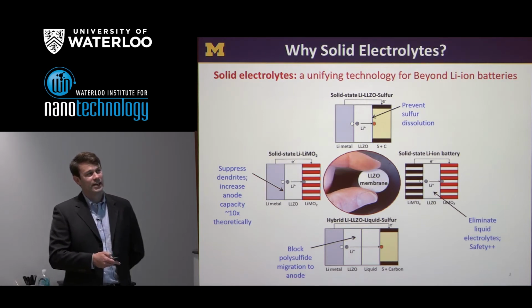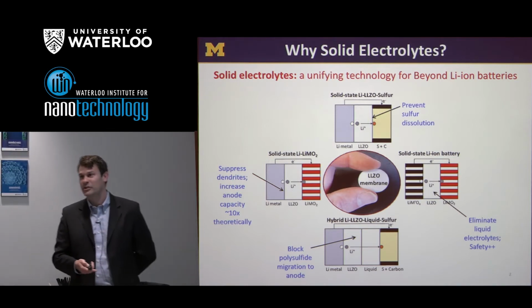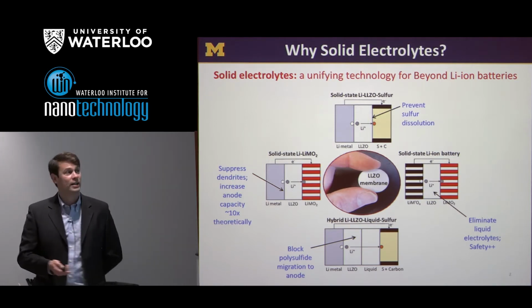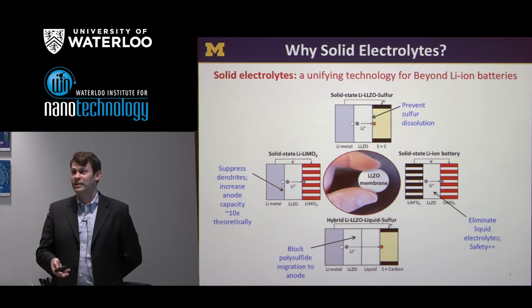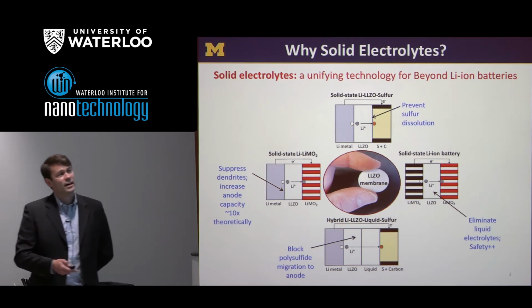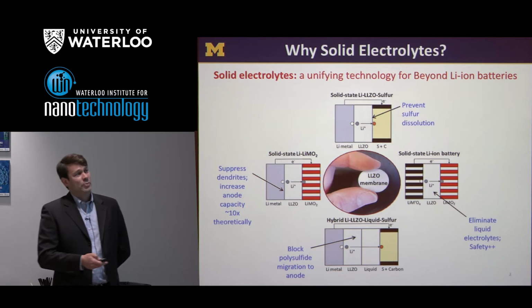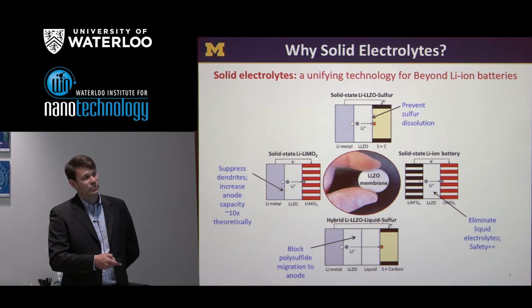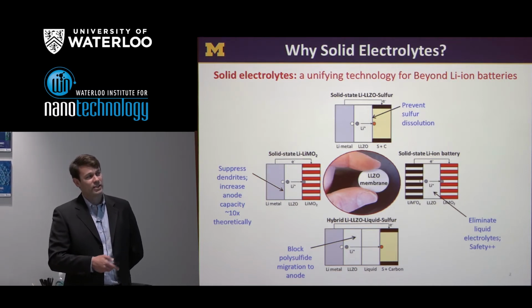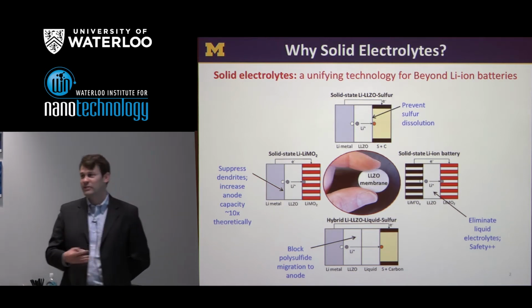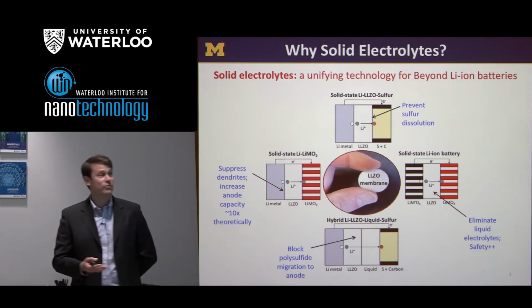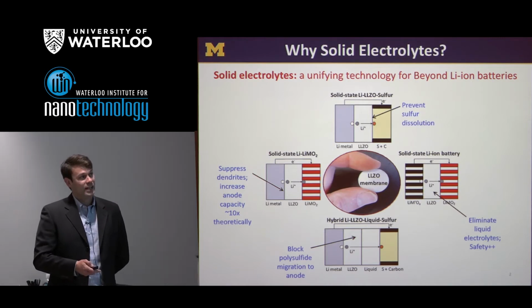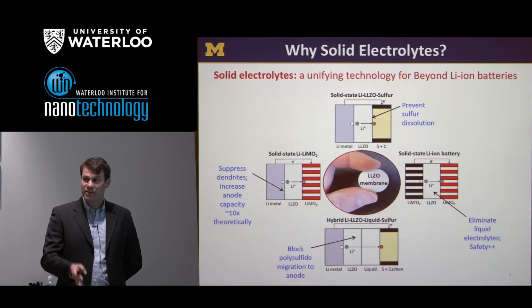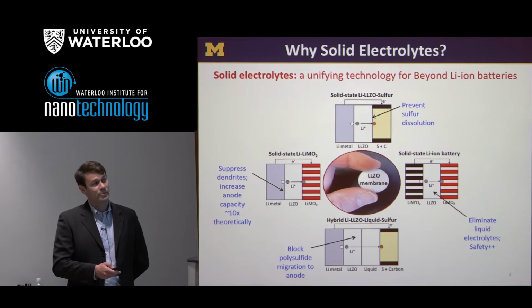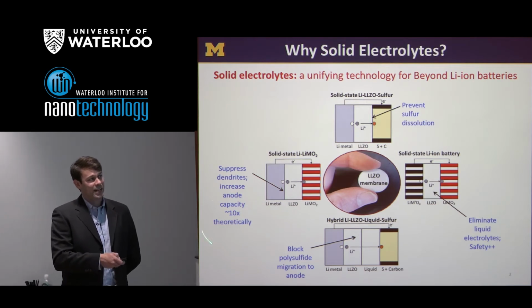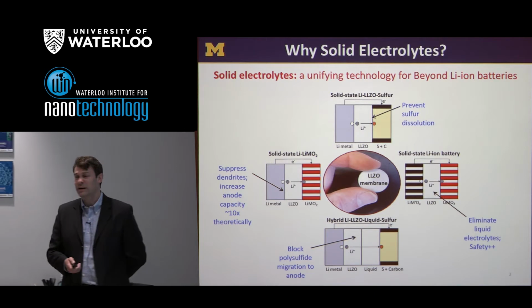So in here I'm mentioning LLZO as a specific example of a solid electrolyte. In fact, this is the composition I'll spend basically all of my time talking about today. I'll tell you more about the details of LLZO in a moment. But the way we get to higher capacity in these batteries would be instead of having that intercalated graphite on the negative side, the graphite of course takes up space, costs us some volume, costs us some mass. Instead, let's remove the carbon and just have a metallic lithium anode. So for example, a metal foil of lithium. That would increase the anode capacity by about a factor of 10 theoretically.